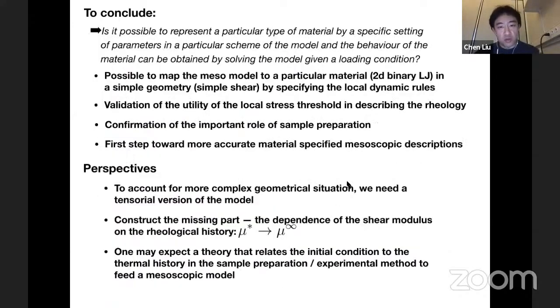Okay, and then I arrive to conclude. So to answer the question that we started with: at the end, we actually find such a scheme of elastoplastic model and a set of parameters that allows us to map, in a simple geometry, the meso model to the particular material that we choose. And from this work, we also validate some hypotheses that have been introduced in the literature, that the local thresholds are important and useful in describing the rheology of soft glassy materials.